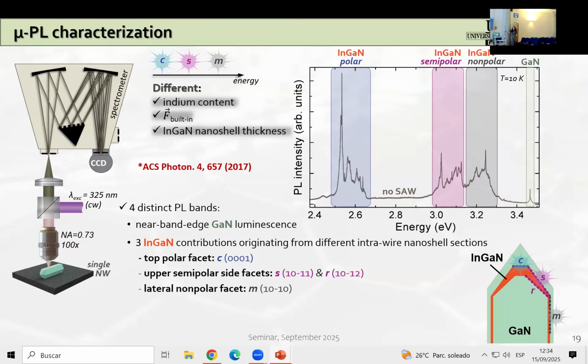Basically, they come from this top polar facet, then this side semipolar facet, and the non-polar lateral facet here. The reason why there is an energetic shift between these three bands is, of course, because each facet has a different indium content. Also, as I mentioned before, a different value of the built-in electric field, and also because, as you can see, the thickness of this nanoshell is different and depends on the facet orientation.